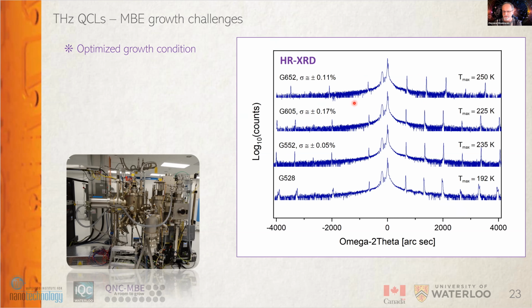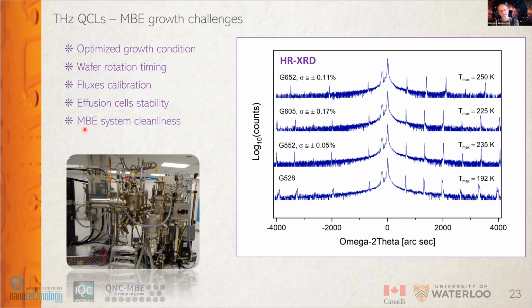They grow almost 20 hours, and stability of the fluxes, all kinds of issues like synchronizing with rotation with monolayers, calibrating fluxes very tediously, effusion cell stability. Those are all key issues, including the MBE system cleanness, which we had to optimize and keep track of in order to get this performance to where we are at this point.